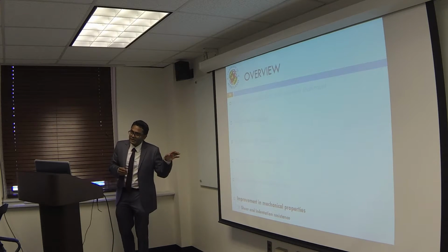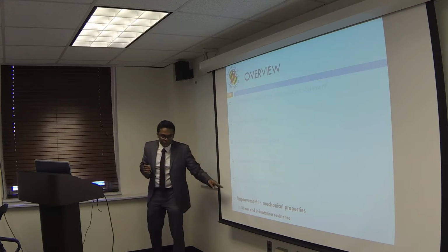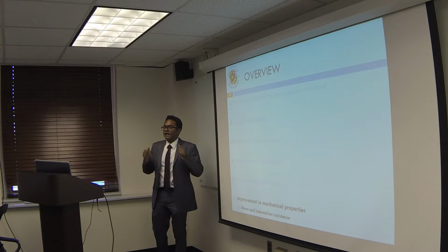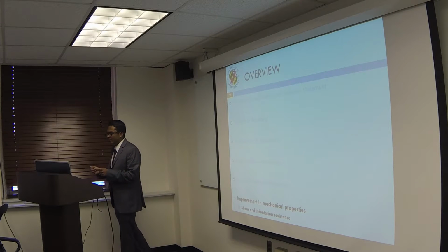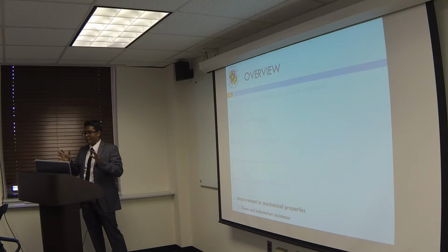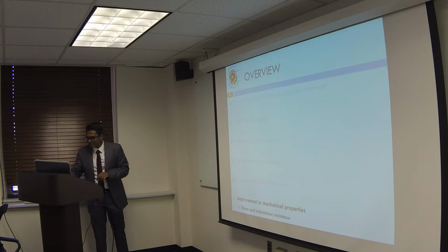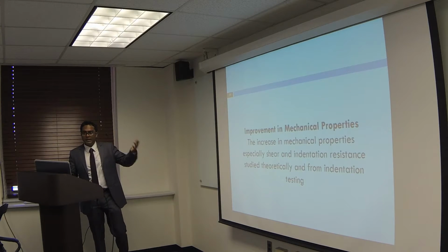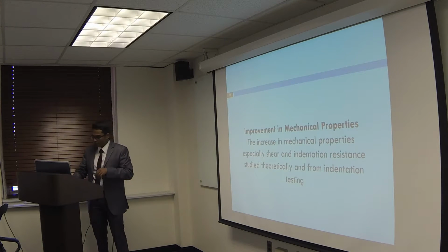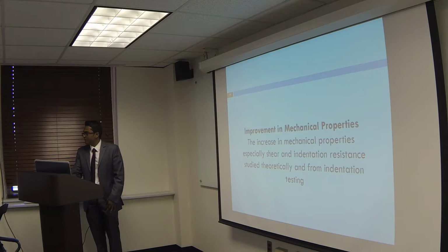But what is really interesting is, if the Poisson's ratio value goes down to -1, it's going to cause an increase in the mechanical properties. And now this leads to a lot of potential for applications. So we wanted to confirm that we indeed saw an increase in the mechanical properties of Galfenol as we reached Poisson's ratio values close to -1.